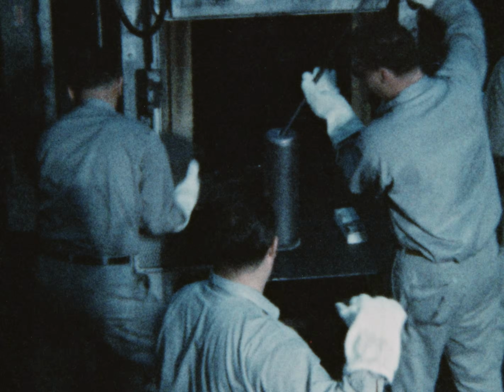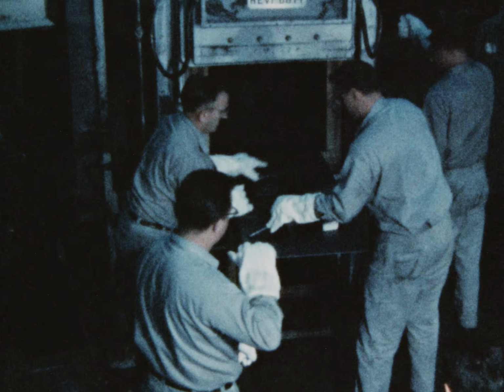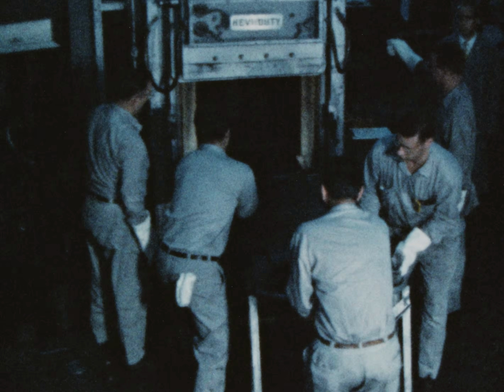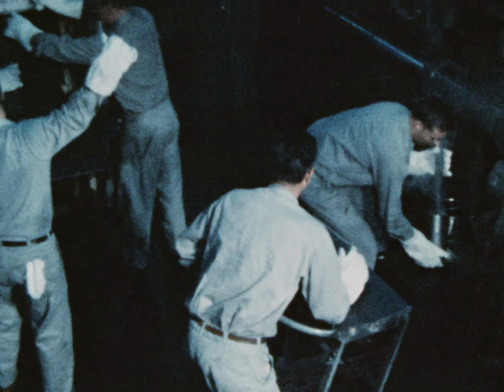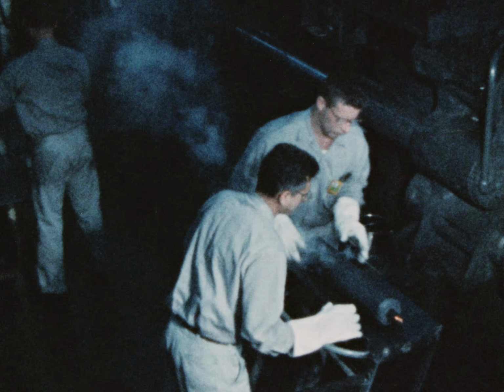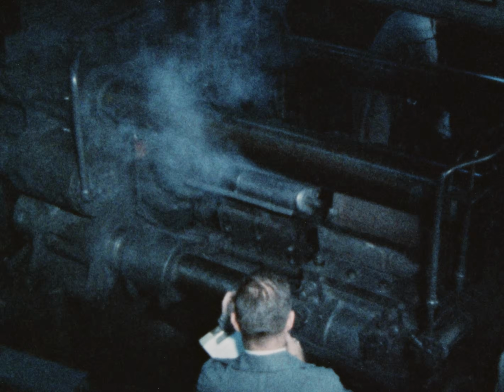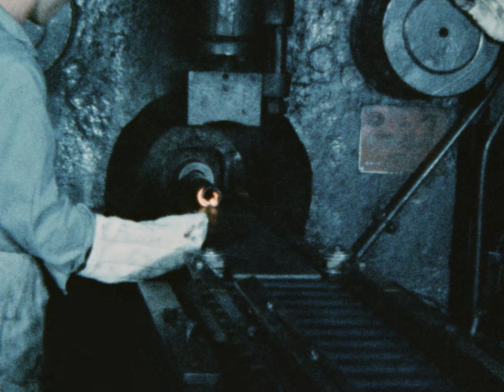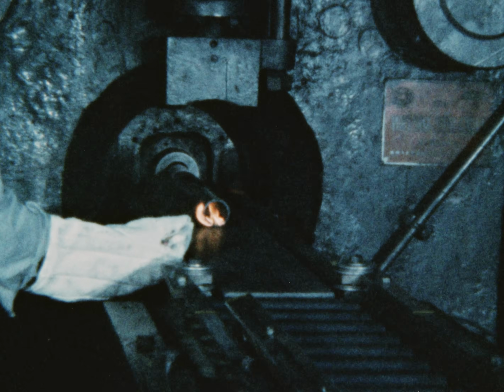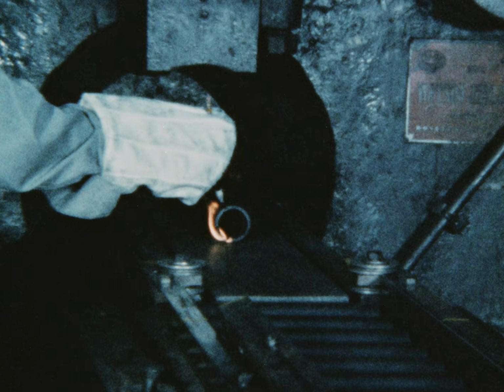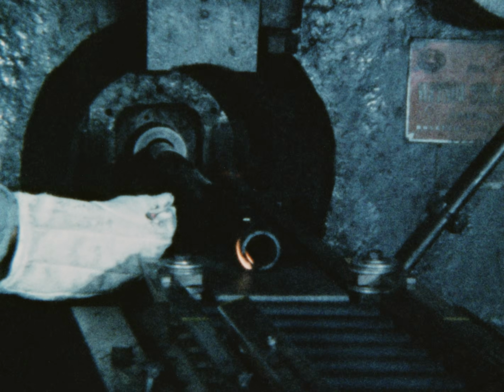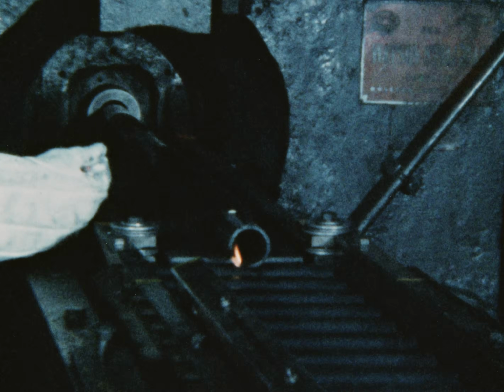The fuel development program included a systematic search for low-cost methods of fabrication. A process of co-extruding tubular fuel elements of uranium metal with a zirconium or zircaloy cladding was developed at Nuclear Metals Incorporated. Proper design of the extrusion billet permitted variation of core and cladding dimensions. Fuel tubes with core thicknesses of 130 to 250 mils and lengths of 10 feet were produced for irradiation tests. Driver fuel and the metallic uranium test fuel for HWCTR was produced by this process.